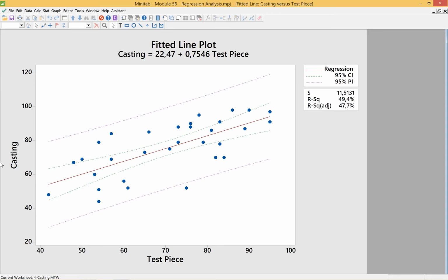And so what we can see from this data is that's actually not a very good test. Why? Well, the test piece is a square block. The casting itself has angles. It's got geometry. It's like the housing of a transmission, or the rear axle, or the head of an engine, or the engine block. And that geometry itself has a lot to do with its strength.